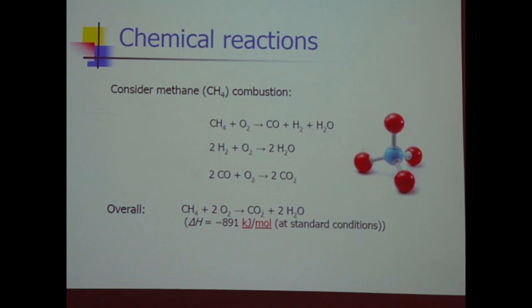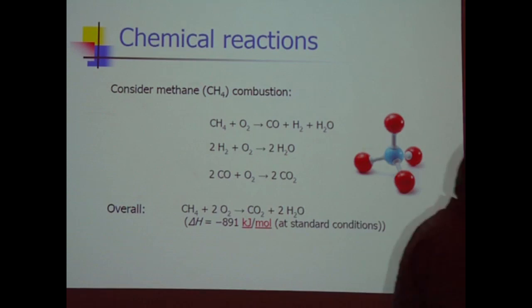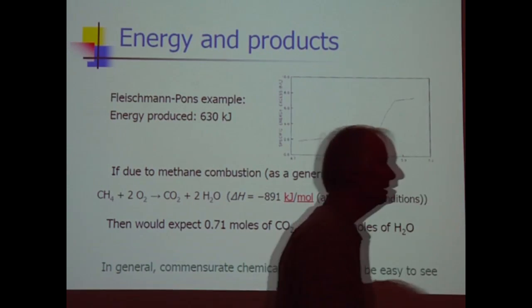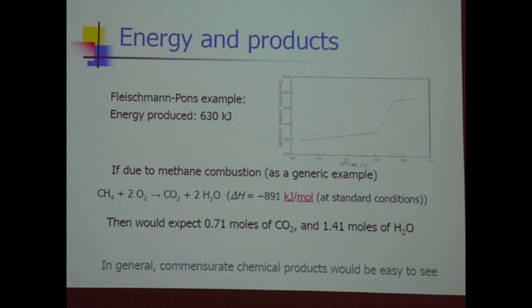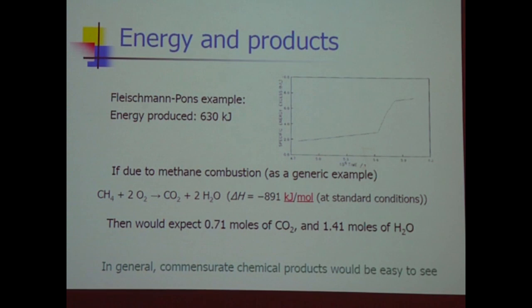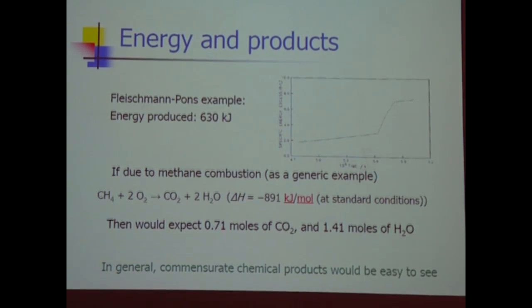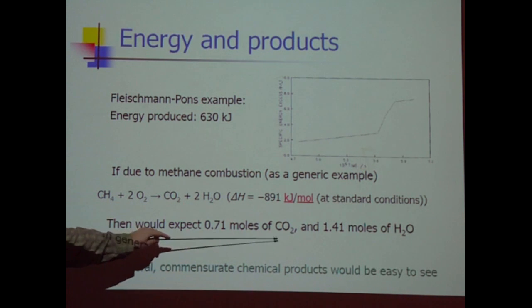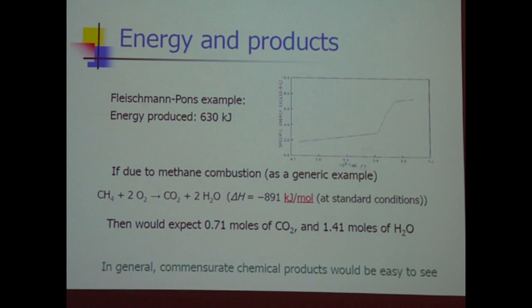So if you have a chemical reaction, for example, combustion of methane, you produce CO2, you produce H2O, and if you make a fair amount of energy, you can make a fair amount of products. So for example, in Fleischmann and Pons's experiment we talked about on Monday, the amount of energy produced was 630 kilojoules. Now, if you believe that that energy was produced chemically, and we can have methane burning as an example of a chemical reaction to stand in, then 630 kilojoules would give you 0.7 moles of CO2, 1.41 moles of H2O. And in general, chemists are very good at seeing small amounts of products.